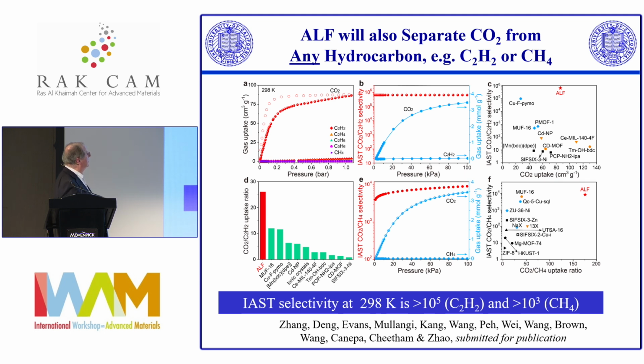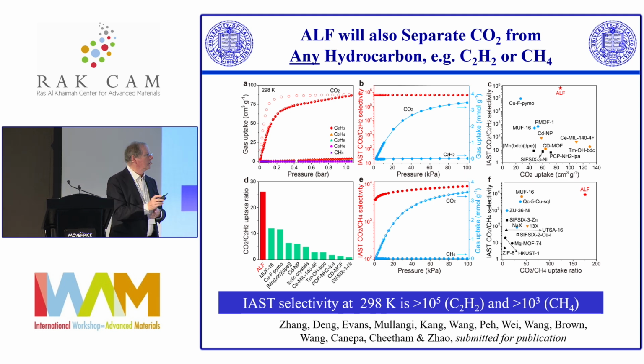So if you look at the selectivity of CO2 against acetylene, the selectivity, which is shown on this left scale here, is almost 10 to the 6. It's absolutely huge. And it's amazing, because the acetylene, it should go in, you would have thought. And then for CO2 against methane, the selectivity is approaching 10 to the 4. It's about 3 times 10 to the 3.